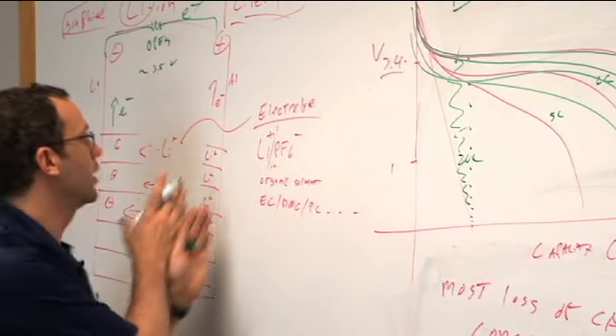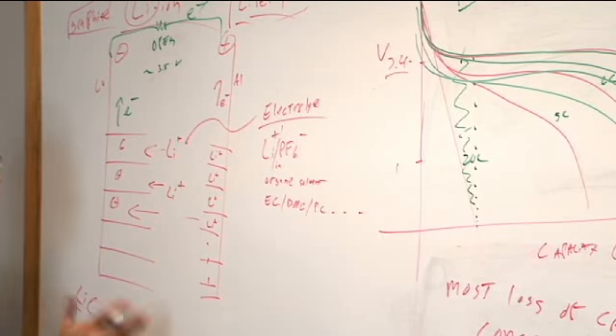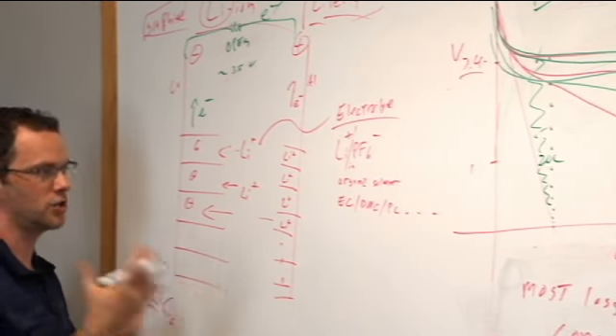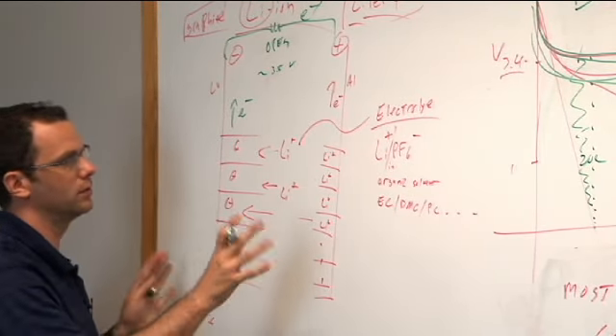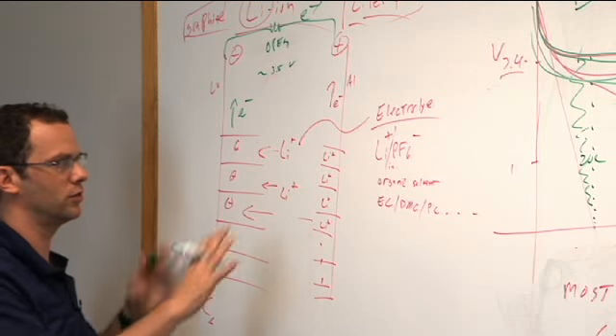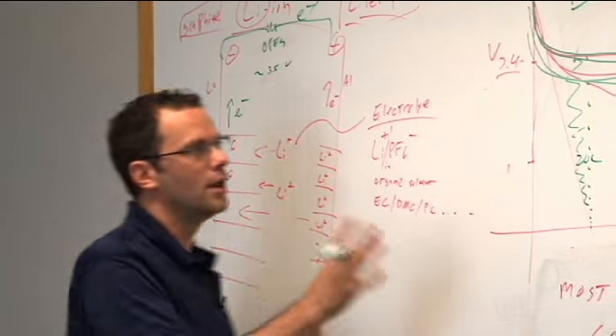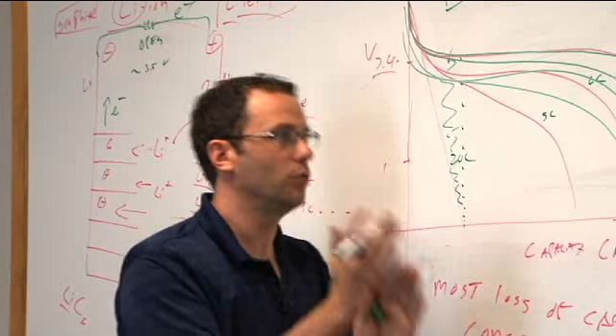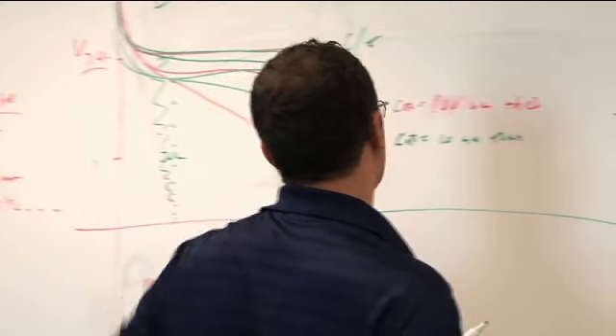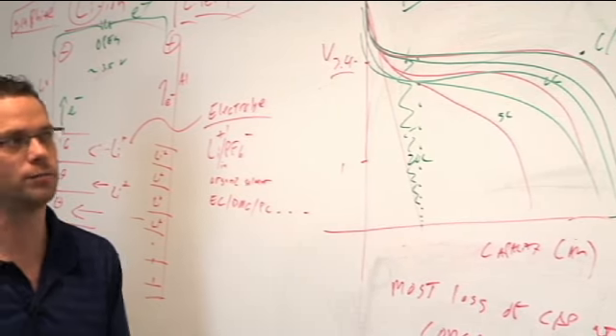And in fact, the intercalation electrode mechanism is very similar to capacitive interaction with respect to the way we talk about electrolytic double layer capacitors in this material system. But the point is that the thinner you go, the better off you are from this standpoint, right? But here's the catch. Why don't we just make really thin electrodes? It's because it costs a fortune, right?